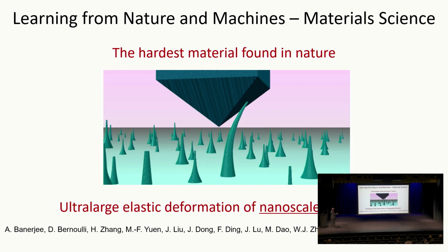So this work was done in collaboration with a group at MIT, a group in Hong Kong, my former postdoc group in Hong Kong, and our group with Professor Ming Dao and a couple of postdocs at MIT. And what we found, to our surprise, was you can actually bend the diamond just like you bend a piece of metal, like aluminum or copper. So the video that you're going to see shows you how the experimental bending takes place in situ in the microscope at high resolution of the nano needle. It also shows on the side a finite element simulation of exactly the same geometry for nonlinear elastic deformation of the diamond needle.